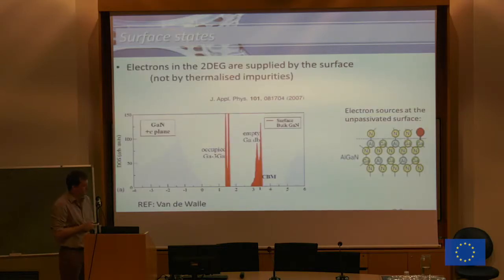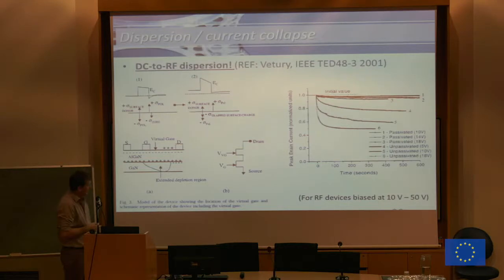So this is a calculation that was done by van de Walle. So this is really first principle calculations on what can exist on the top surface of such a structure. And it is clearly shown that for a number of given configurations, like the ones here, the gallium dangling bonds and so on, you do create states in your band gap that can give up these electrons into your channel. So any imperfection here can be a source of these electrons, can be a state that donates electrons to your channel.